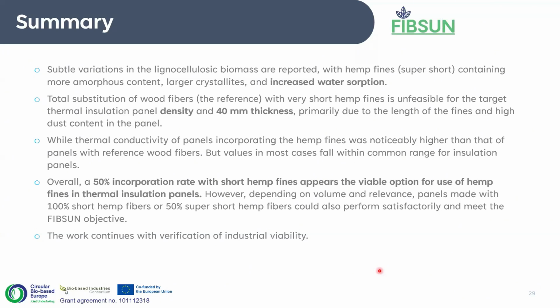And while we see that the thermal conductivity is high for the hemp panels, these values fall within the common range for insulation panels. So it means that while this material is not as proficient as the wood fibers, it still falls within the range of materials for this product. And then overall, 50% incorporation would work for the short fibers.